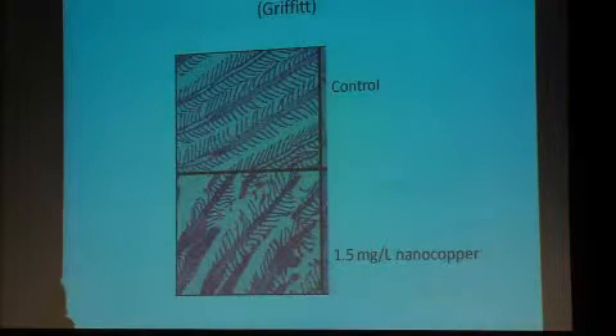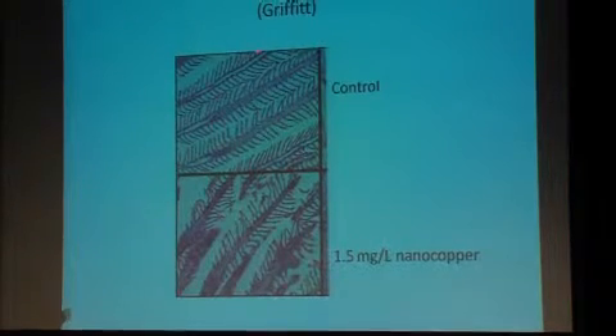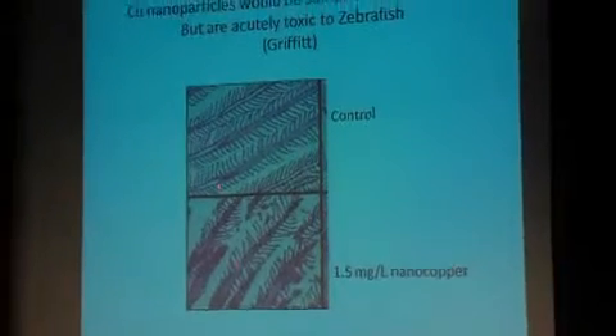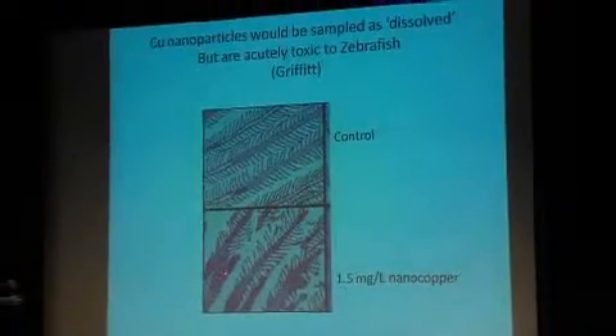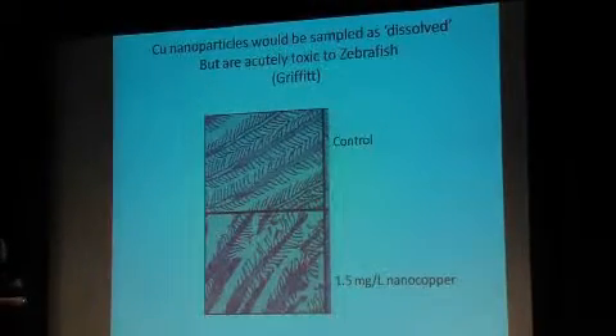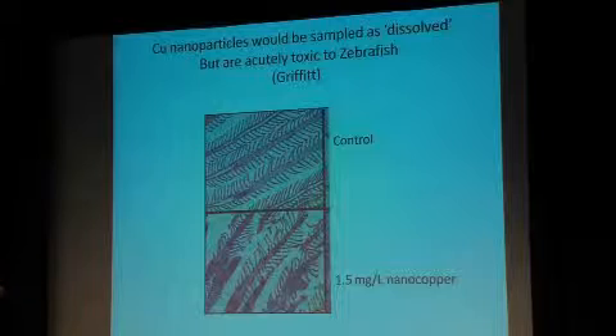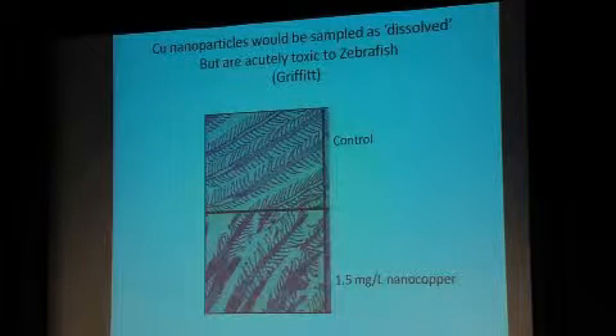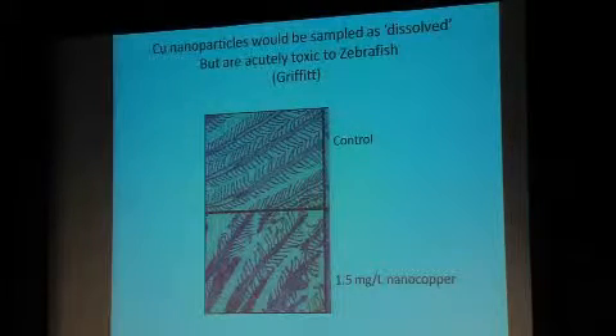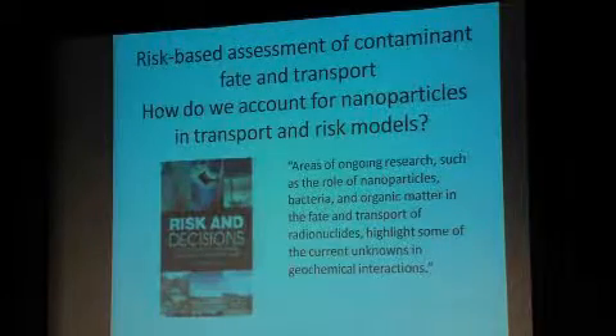Copper nanoparticles, in fact, have different toxicity than dissolved copper. Here's some zebrafish gills, a control. The nanocopper nanoparticles actually can get in there and disrupt them. They can be quite toxic, and their toxicity is far more than dissolved copper. And you can consider the dissolved copper in this.